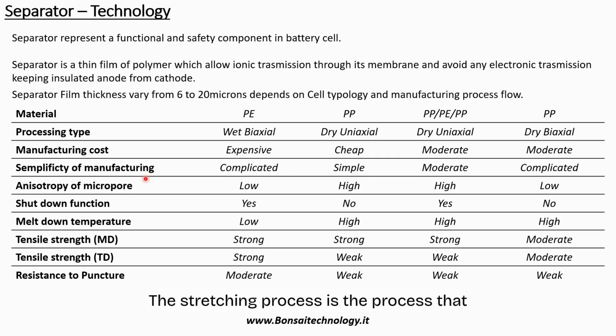The stretching process is the process that allows us to obtain the microporosity or the nanoporosity inside the separator, because there is a system that stretches the material and then the fiber, and this creates the porosity. So we can say that the stretching process is one of the most important processes in the separator manufacturing. In terms of manufacturing cost, the wet process is the most expensive, and the dry is less expensive. We can say even that PE is more expensive than the PP material.